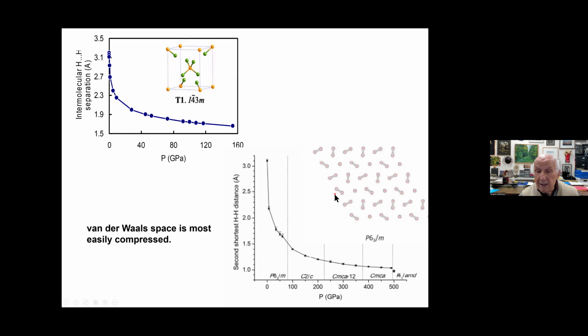What you see at lower right is the same thing for H2 molecules. Now, this is solid H2, which is only available at low pressure, at low temperatures. These little dots here are not hydrogen atoms. That's an H2 molecule, which you're seeing from the top down on a diatomic. It's a projection, but the rest you see. And the distance I'm talking about is not the bonded distance, which you and all of your students know as 0.74 angstroms. It is the shortest contact from one hydrogen to another hydrogen of another molecule. It's the lowest non-bonded contact, and that's what's being plotted here. It starts at the 3.1 angstroms again, and in the first 10 gigapascals, it goes down to below 2.